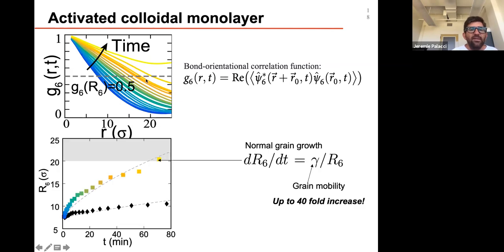This value of 1/2 is arbitrary. We just need a value high enough to make sense, in the sense that we're still in the same crystal. We tried 1/3, 1/2 or 2/3, and it makes zero difference. If you take a very small value for the cutoff, you end up dominated by noise. If you require G6 to be equal to 1, then it's only true if the whole system is converted, and you have finite size issues. So we took 1/2, but we made sure that the results I'm going to discuss are not depending on that parameter.